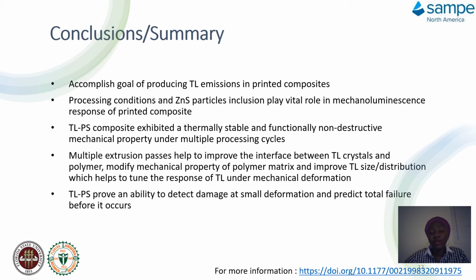And the multiple extrusion cycle shows a better improvement in the interface between the TL crystals and the polymer, because it helps the energy to transfer from one crystal to another, and also modifies the property of the composite. And this helps the composite to exhibit a higher signal at the third processing compared to the second and the first processing. And all together, with TL composite material, we can easily detect small damages in a structure without complete total failure of the whole structure.